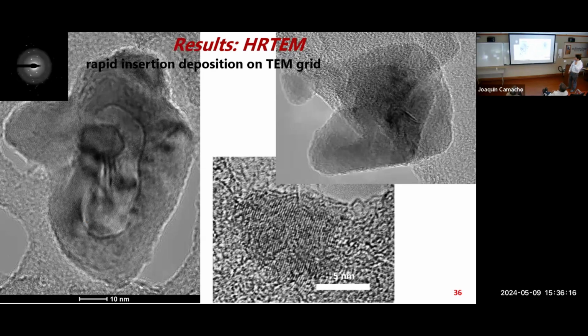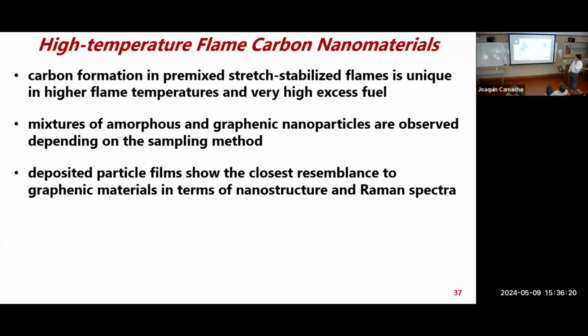And yeah, some more examples of these graphene-like graphite structures can be observed. So to summarize this part, the stretch-stabilized flames are high temperature, and if you want to get soot formation at these high temperatures, you have to go to very high equivalence ratio. That offers a unique situation where we observe both soot formation in the flame and deposition of anything from amorphous to graphite structures, depending on the specific condition.